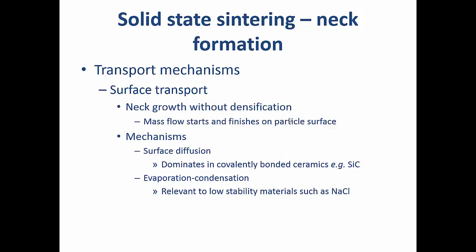If we start by considering surface transport mechanisms, these give rise to neck growth without densification. Mass flow starts and finishes on a particle surface. If it's surface diffusion, this is the sort of thing that dominates in covalently bonded ceramics such as silicon carbide. An evaporation and condensation mechanism is the sort of thing that you would see in sodium chloride, which is a material that's been studied from a scientific perspective in terms of its sintering behaviour.